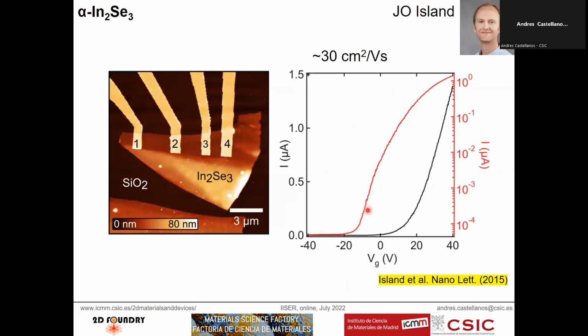This material can be exfoliated similarly to molybdenum disulfide, graphene, etc., in the shape of flakes, and then you can do your microfabrication to put electrodes and measure your field effect transistor characteristics. One of the first things you notice is that this material gets decent enough mobilities, 30 cm² per volt per second. And usually we perform these kinds of measurements in a 2-terminal configuration. Well, 3-terminal configuration with the gate.